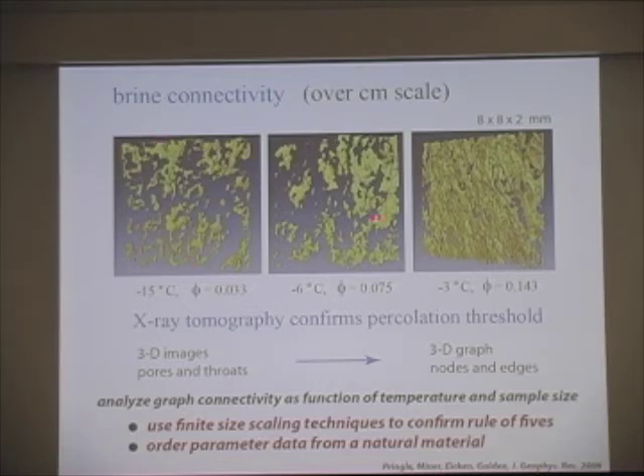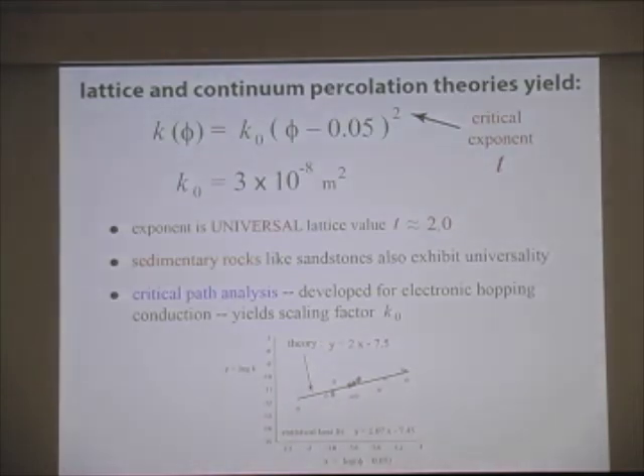So here we have no pathways, one pathway, many pathways. So we take this 3D X-ray tomography data, we map 3D images of pores and throats onto 3D graphs of nodes and edges, and ultimately we can confirm this rule of fives. And then we use a lot of lattice and continuum percolation theory and solid state physics and other areas in theoretical physics to come up with a deceptively simple formula for the fluid permeability, the vertical component of the fluid permeability of sea ice, as a function of brine volume fraction. So there's the 5% right there, that's the threshold. And then there's a two that's called a universal critical exponent, which actually holds for lattices, but it's kind of amazing that it holds for a real material like sea ice, but we can calculate that out and show that that's supposed to be the case.